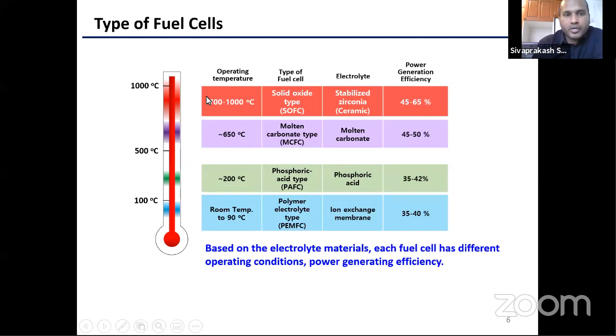Solid oxide fuel cells work at 700 to 1000 degrees Celsius. The main difference is the electrolyte material. Here, stabilized zirconia or a ceramic membrane is used as the electrolyte, which has an efficiency of about 45 to 65% for power only. When combined with heat turbine engines and capturing the waste heat, the efficiency can move over 90%.